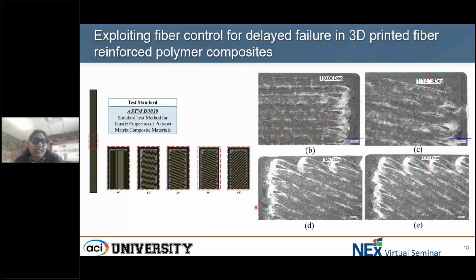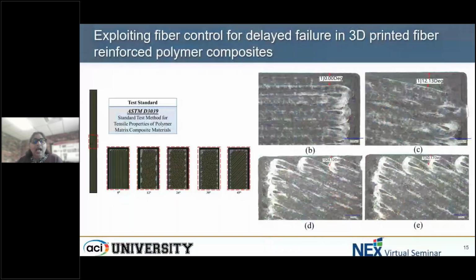So, as I was talking about accuracy, how do we determine whether the orientation that we require is actually getting onto the bed, right? How do we know whether the orientation that we ask the G code to extrude onto the print bed, how do we know the accuracy of it? So we've done some microscopic investigations to see how the fiber is actually aligned with the thermoplastic.